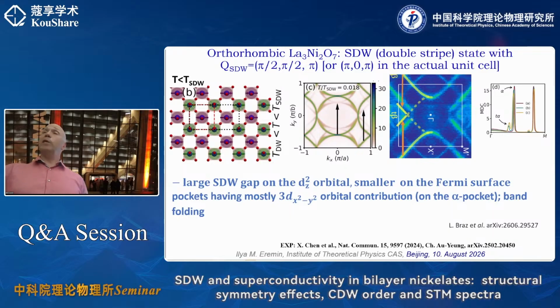You can explain why TC is going down, right? Because in this case, you get this S plus minus pairing, but between these two outer layers, and that explains immediately why TC is so low, and so, this kind of things. But then, okay, so what happens in a trilayer in that case? How to transform this Zhang-Rice singlet and three-spin polaron in the trilayer picture? I don't know.